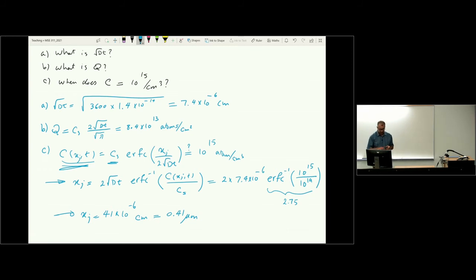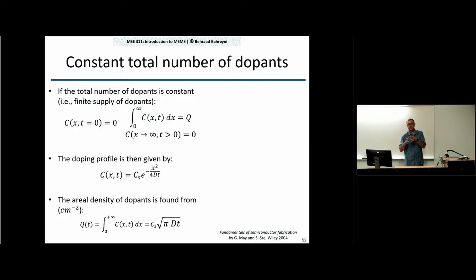In this case, I'm going to have dopant atoms, a certain number of them, brought to the surface, and then I provide the environment for them to diffuse into the substrate. So in this case, I'm not providing an infinite supply of the atoms. I have a certain number. So let's say I deposit a film that has this many atoms of phosphorus in it, right? I deposit this film on top of my silicon, and then I just raise the temperature so that those phosphorus atoms can penetrate and diffuse into silicon.